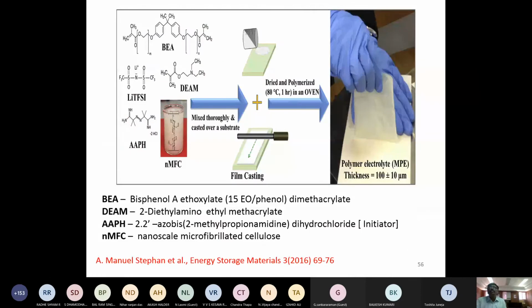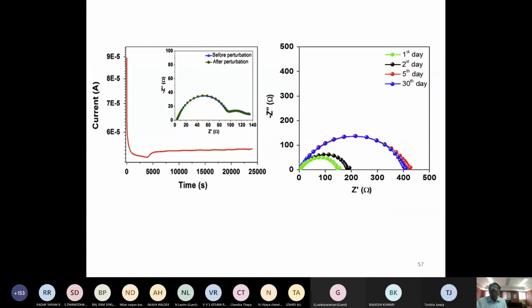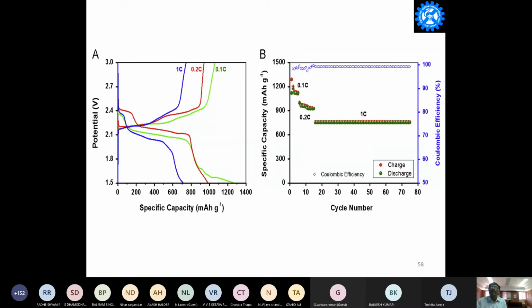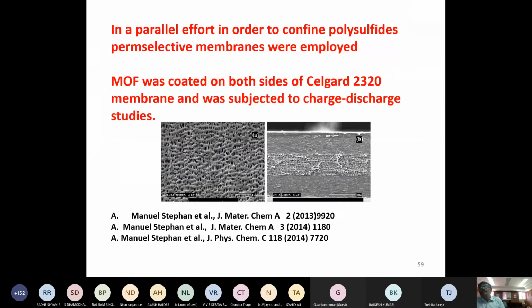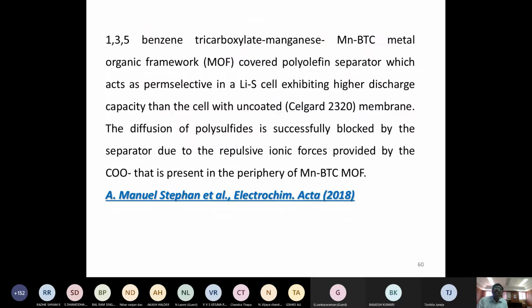So what we have done is, we have used bisphenol A ethoxylate dimethacrylate, and we made a solid polymer electrolyte. And we have made some characterization studies like transport number and compatibility with the lithium metal anode. And finally, we have subjected these gel electrolytes between the electrodes, and we were able to do only 75 cycles, and the capacity fade was very fast, so we could not use it. So the second thing we have done is, we have taken the porous membrane, that's what we are using in the lithium ion battery, and we have coated it with suitable perm selective membranes.